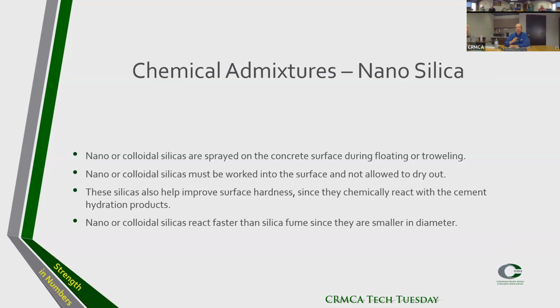Another one, and to be fair, I am not too familiar with them, but I picked that up from one of our larger ready-mix suppliers, is they suggest to use nano or colloidal silicas that are sprayed onto the surface during floating and troweling, meaning that these nanosilicas, they are worked into the surface. So they should not be applied afterwards and dried out. They need to be worked into the surface. Generally, these silicas help to improve the surface hardness because they chemically react with the cement hydration product. So at the very top surface, you get a harder surface. And what I heard is that, like in warehouse floors or so, this is something that is quite often applied. Generally, nano colloidal silicas react faster than silica fume. And I heard that you should not use silica fume for these applications. It should be really nano or colloidal silicas for the surface hardening.